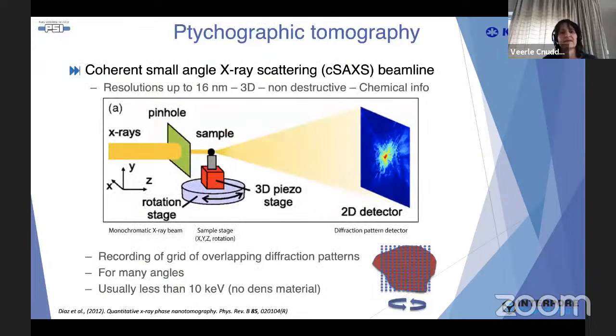That is why we experimented with coherent small angle X-ray scattering, or CSAXS, at the Paul Scherrer Institute in Villigen, Switzerland. There is a CSAXS beamline where you can reach resolutions up to 16 nanometers in 3D, non-destructively, and it provides chemical information. If you look online, it's also sometimes called nanotomography, ptychographic tomography, or small angle X-ray scattering.